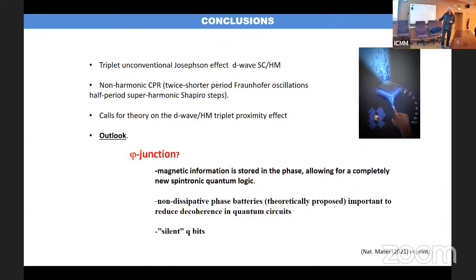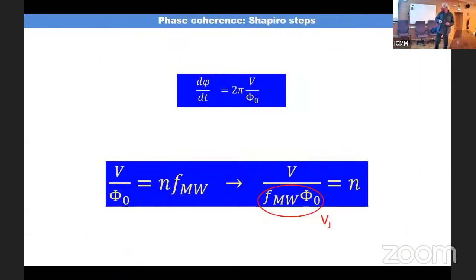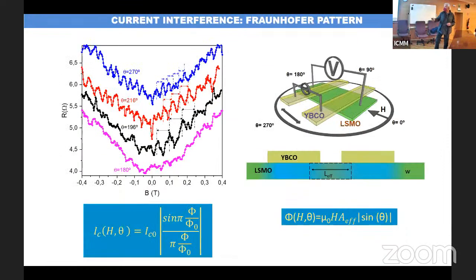Very good. Let me go back to this. Here, the normal state resistance of the junction is of the order of one ohm, right? And this is the modulation that you expect if you measure below the critical current. When the critical current goes to zero, the resistance of the device goes to the normal state resistance, one ohm. Practically, this is difficult to measure. So what we do is we measure slightly above the critical current, but we still feel the modulation of the critical current.